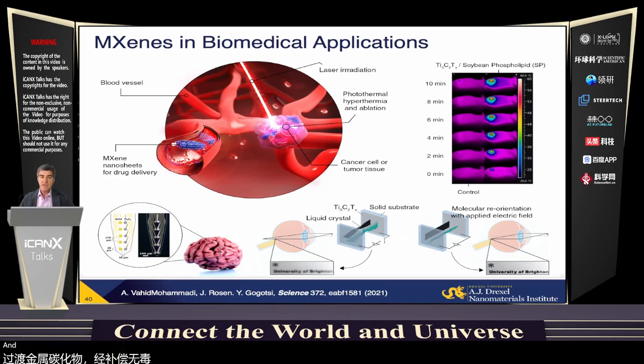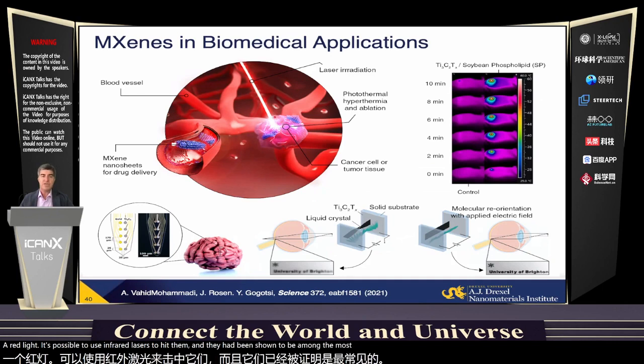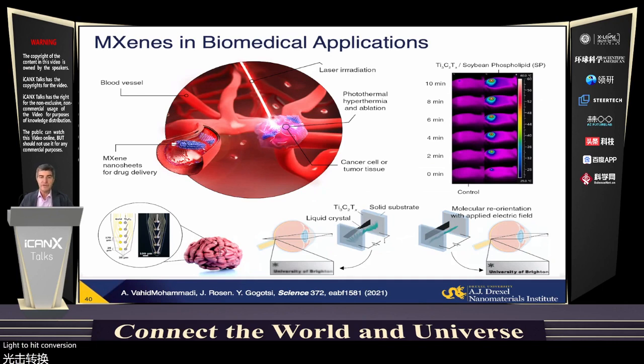And you remember I mentioned, for example, 780 nanometer transverse surface plasmon in titanium carbide Ti3C2. In many other materials, they move to infrared, near infrared range. So it's possible to use red light. It's possible to use infrared lasers to hit them. And they have been shown to be among the most efficient light to heat conversion materials here, destroying tumors, and they can be used in photothermal therapy.